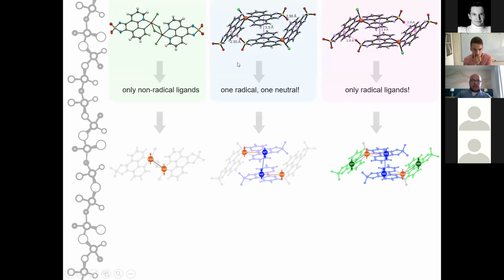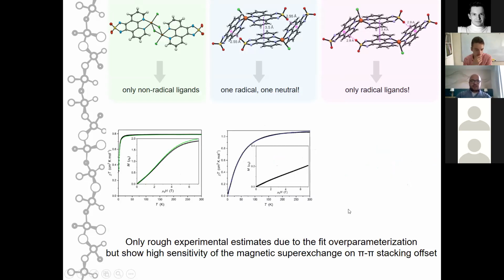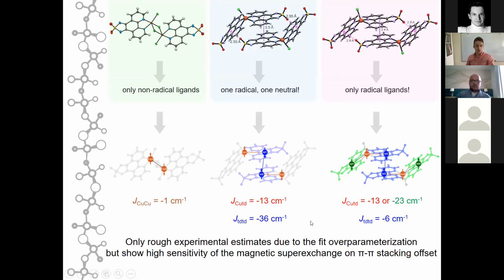So after we identified where our magnetic centers are in these molecules, we managed to analyze the magnetic data for all these compounds. And we have also used some DFT methods, which I'm not going to mention here, but we managed to calculate that the interaction between the radical anions in this pi-pi stacking conformation is very weak. And again, this is in contradiction to what we observed for simple salts, for potassium salt and PPN salts of some of our previous radical anions, but is in line with the fact that the pi-pi stacking offset actually controls these antiferromagnetic interactions between the pi-pi stacked radical anions.